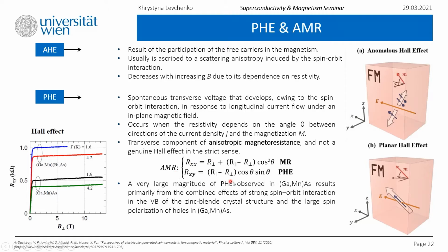And both of them depend on angle theta between the direction of the magnetization and the current. In the equations, R parallel and R perpendicular correspond to the resistances when the current is either parallel to the magnetization or perpendicular to the magnetization. There are two main reasons for this effect: spin-orbit coupling and magnetization. So let us see how this phenomenon looks during the measurement.